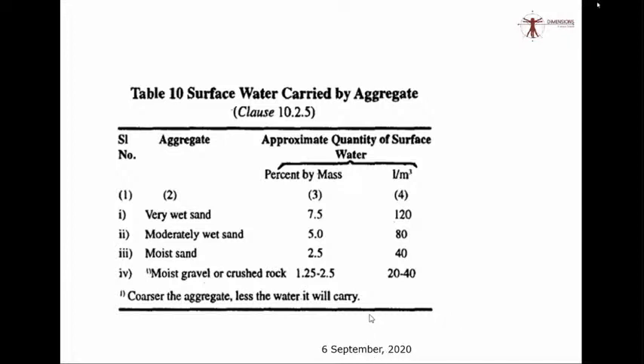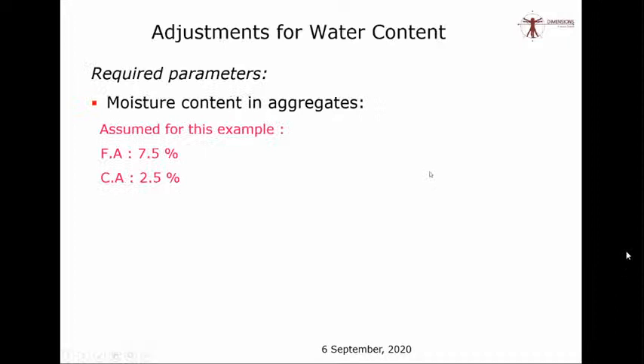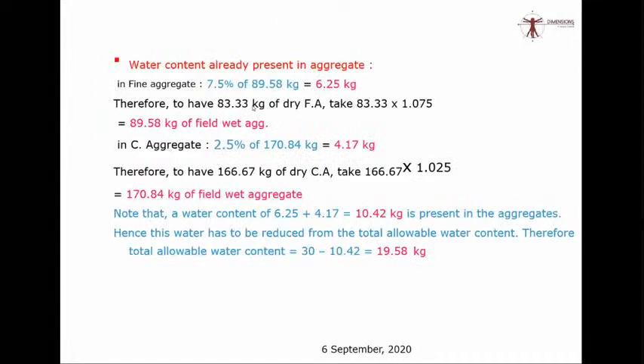Now, to understand this better, I have assumed a moisture content of 7.5%, which is mostly the case when you get fresh sand either from the riverbed or even from an M sand manufacturer. Mostly it is having 7.5% of moisture, and I assume 2.5% moisture for coarse aggregate. And now, what is the correction I have to do? Instead of 83.33 kg, I will take 89.58 kg of sand.